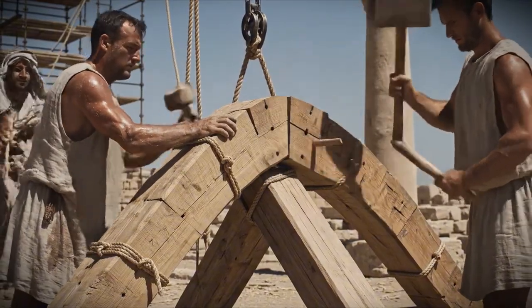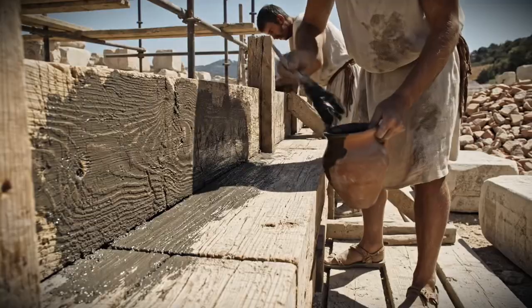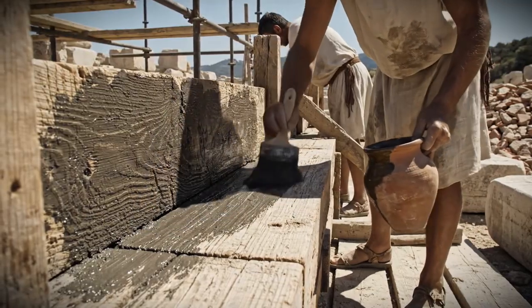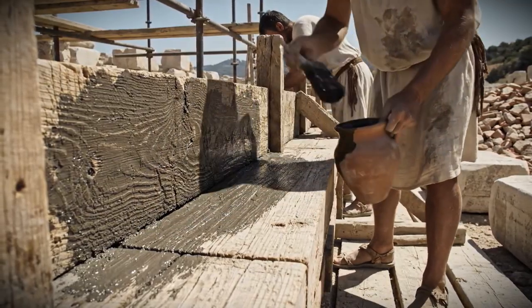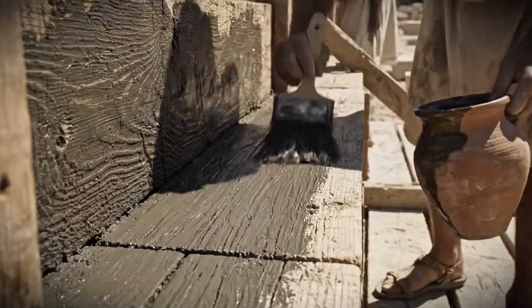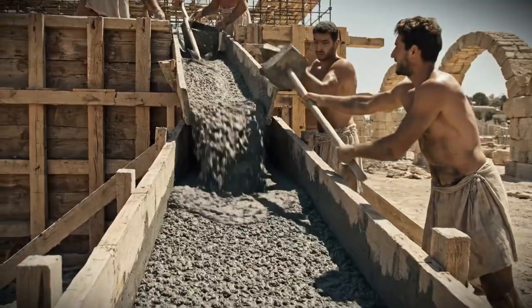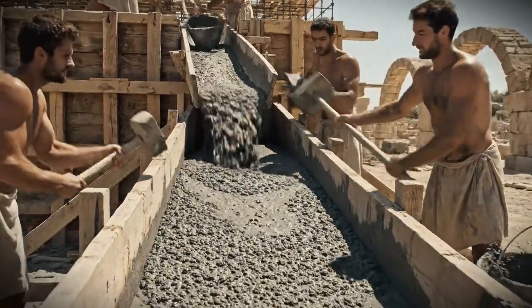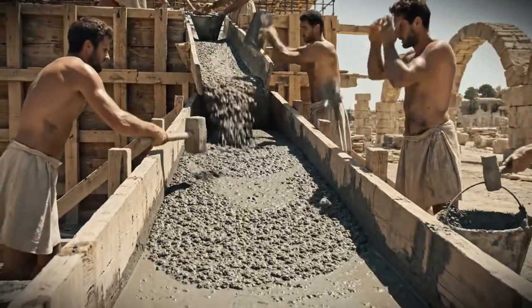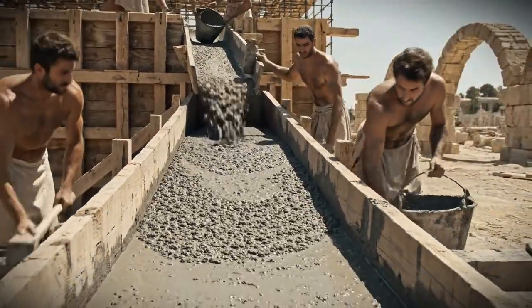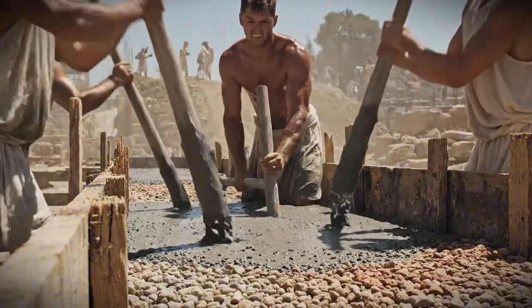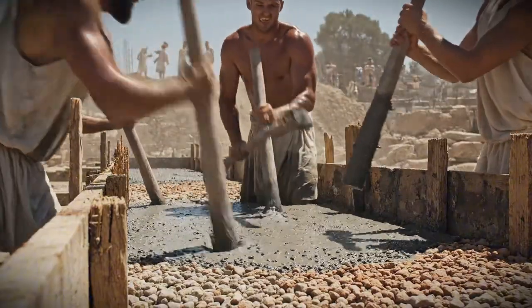The typical mixing ratio for structural concrete followed what we'd call a 1:2:3 proportion: 1 part lime to 2 parts pozzolana to 3 parts aggregate. But this varied significantly based on application. For waterproof cisterns and aqueducts, the ratio might shift to 1:1:2, increasing the pozzolana content to enhance hydraulic properties.